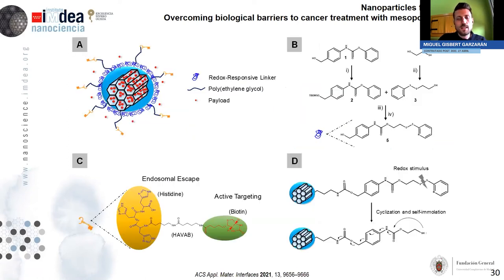So for that, we engineered this system. So basically we have, again, MCM41 mesoporous silica nanoparticles that are functionalized with a redox-responsive self-immolative linker, which is this molecule. So this molecule is multifunctional, meaning that it can slow down premature drug release, and also it provides reactive points for further functionalization. Then we have polyethylene glycol, which is a very biocompatible polymer. And finally, we have this key. So this key is this molecule.